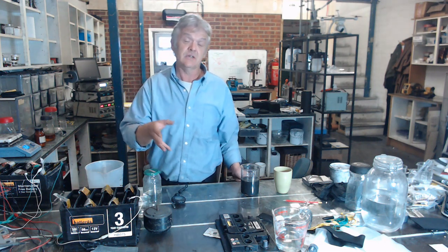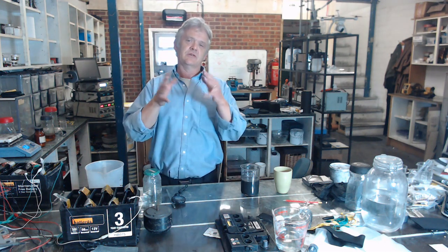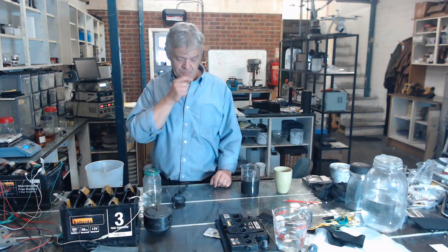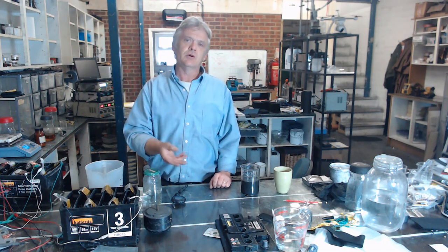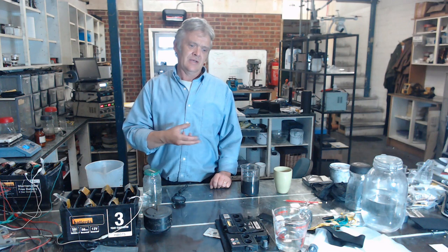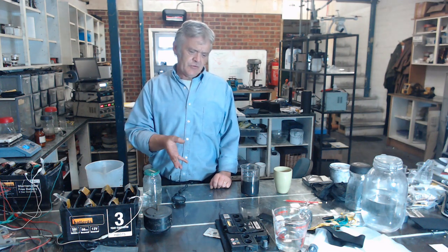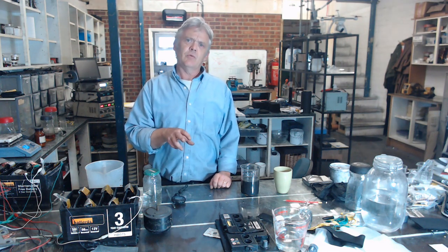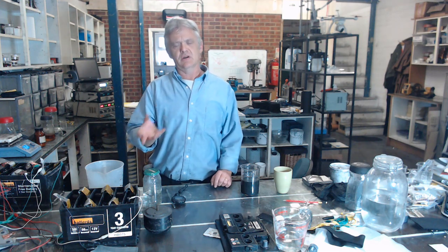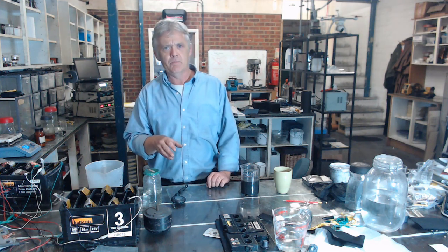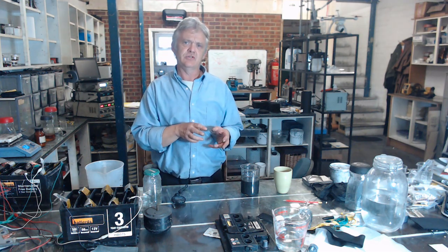Now, graphite itself will melt in a non-oxidizing condition at 3,550 degrees, and it's how they think vein graphite works. Incidentally, it's being volatilized and recrystallized at those temperatures. So that's a really interesting process, obviously very capital expensive. If you want to purify it beyond 94%, what they tend to do is a chemical leaching of any of the other stuff that's left in there, and that gives you the higher percentages.